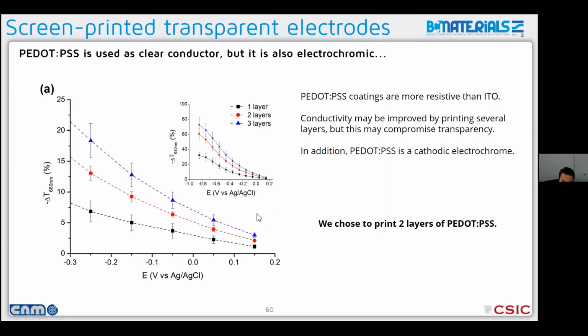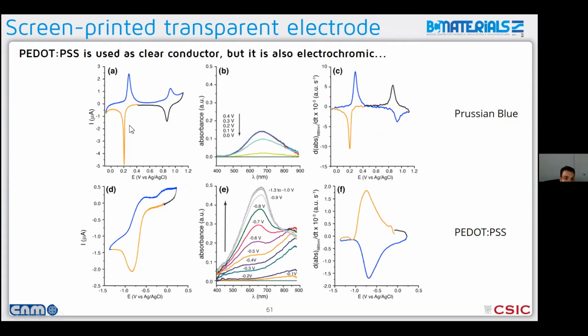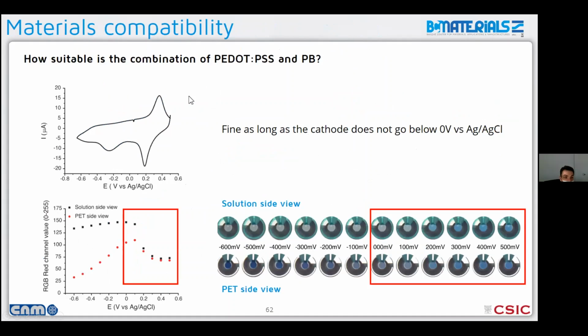But it's a very good electrochromic. I mean, that's why it's also used in electrochromic displays, because it doesn't take a lot of voltage, and it turns into a very deep blue color. The problem is that it's cathodic. So we had to see where these color changes were taking place, and make sure that the PEDOT electrode would not mask our main color change, because at the end of the day, we were going from blue to colorless, and here we're going from colorless to blue. So when we combine the two materials, you still get the nice Prussian blue signal and the signal due to PEDOT:PSS.